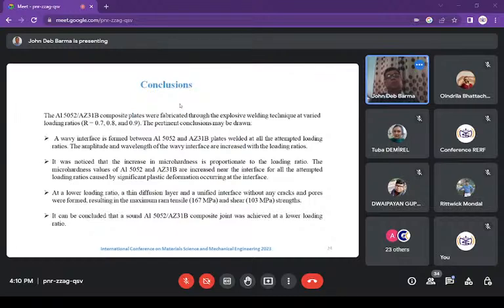As already mentioned, the composite plates were fabricated through explosive welding techniques at varied loading ratios, and these are the conclusions which you can draw. We have seen the wavy interface that was formed between the aluminum 5052 and AZ31B plates, which were welded at all attempted loading ratios, that is 0.7, 0.8, and 0.9. And it was noticed that the amplitude and wavelength of the wave interface increased with the loading ratio.